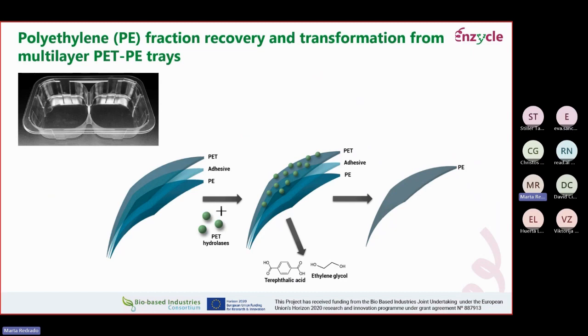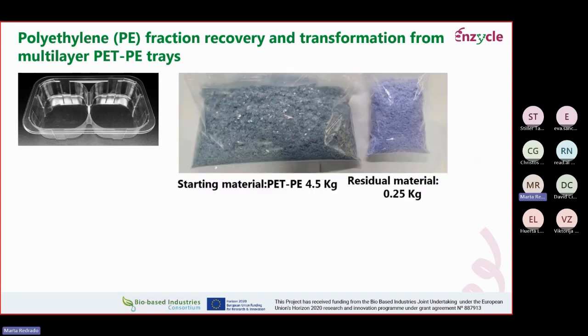So we have not been able to tackle the issue of enzymatic depolymerization of polyolefins, but what we can do is eliminate the PET fraction from a PET polyethylene tray, which is good because if we eliminate the PET, we end up with the polyethylene. And once we have the polyethylene, we can do mechanical recycling with it to produce, for instance, films. So this is an example of a starting material on your left.